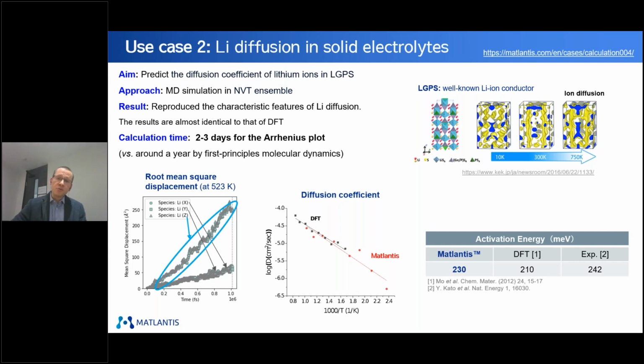And you see we will produce what is well known, which means that the lithium ion will diffuse along the z-axis, which is the curve, or let's say the data that is in blue. And on the x and y axis, you will see a much smaller root mean square displacement. We also calculated diffusion coefficients.